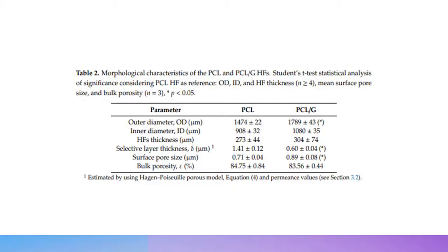The higher viscosity of PCL graphene dope solution with respect to PCL dope solution may have produced a higher shear stress in the extrusion needle, causing the expansion of the internal and external diameter of PCL graphene hollow fibers, as shown here in the table. Bulk porosity in both hollow fibers was above 80%, similar to the other polymer scaffolds manufactured by phase separation, which guaranteed the uniform supply of nutrients to cultured cells. Here in Table 2, it summarizes the results obtained from the morphological characterization of porosity of the hollow fibers.